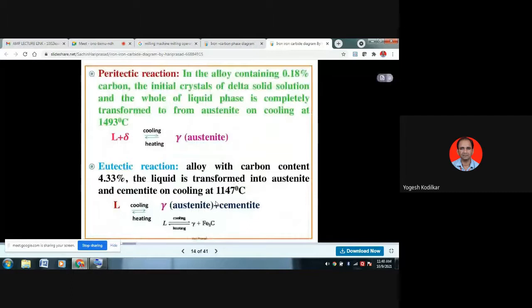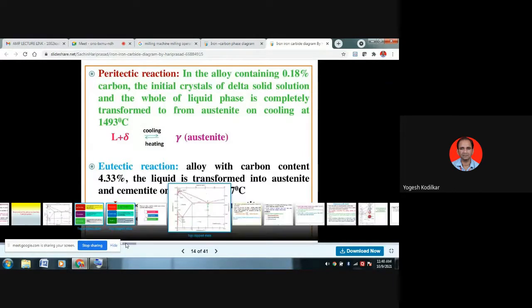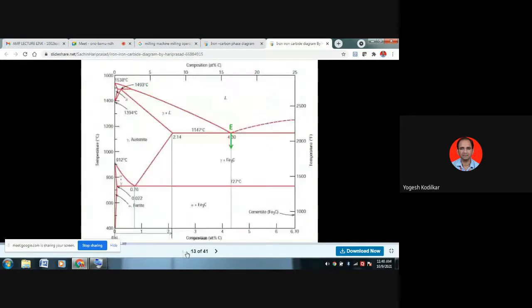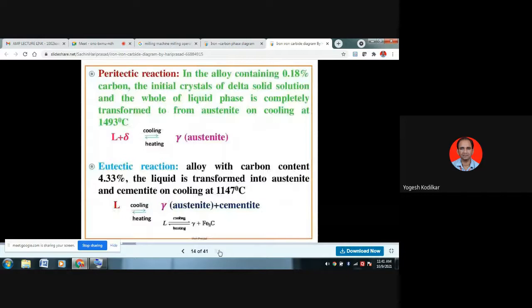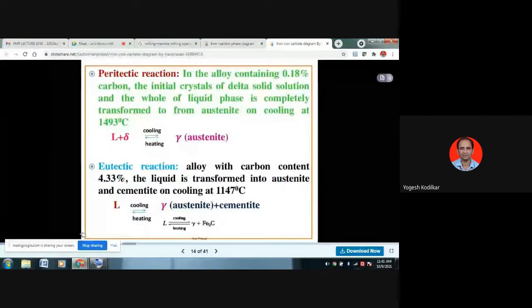The peritectic reaction occurs in the alloy containing 0.18% of carbon. The liquid phase plus delta solid solution is completely transformed to austenite on cooling at 1493 degrees Celsius. At this temperature, liquid plus delta phase gives rise to gamma austenite. And the second reaction is the eutectic reaction. This is the high temperature peritectic reaction.